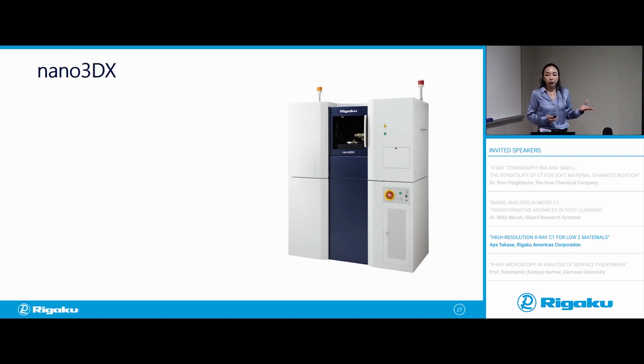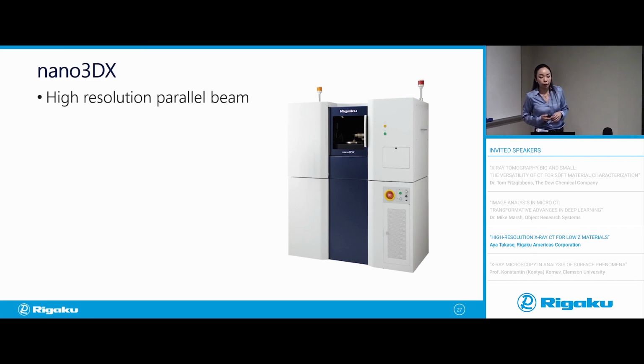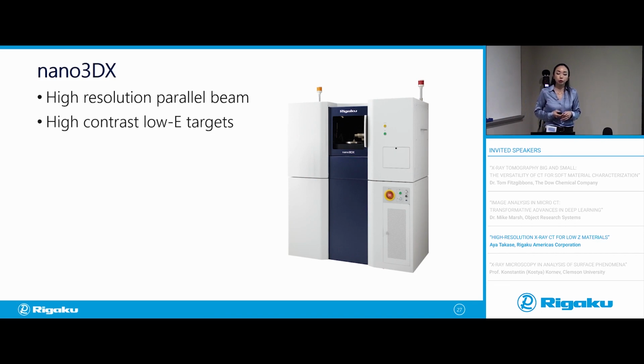But the Nano 3DX uses a different X-ray source and different geometry to specialize in low-Z material high resolution imaging. So this system has a high resolution parallel beam setup, and it uses high contrast, low energy targets such as chromium, copper, molybdenum, in addition to tungsten. And it uses a high power source, to be specific. The Nano 3DX uses a 1200 watt X-ray source.